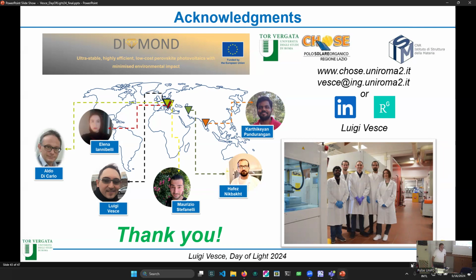So thanks for the question. The flexible perovskites are really interesting, no? Because you have a huge application. The main drawback of this technology is because of the substrates, because the substrate is in some way weak with respect to the permeation of moisture, for example. So that's why, for this kind of technology, something is already visible, but not with perovskite, with the pure organic photovoltaics, for some indoor application.